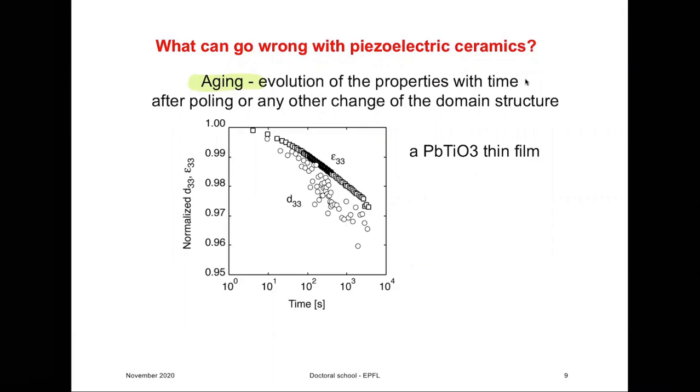So here is an example. This is d33 and epsilon33, so longitudinal permittivity and longitudinal piezoelectric coefficient as a function of time in a lead titanate thin film, where we measured it after applying some field pulse to it. And you see that both drop approximately linearly on a log time scale. So that's called aging, and it has to do with either a reorientation, readjustment of domain walls in the material